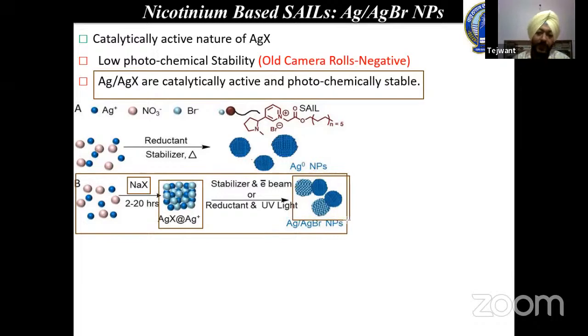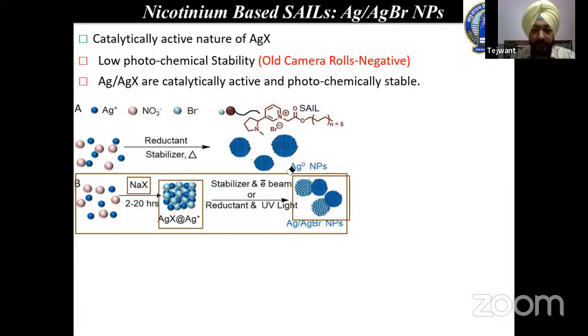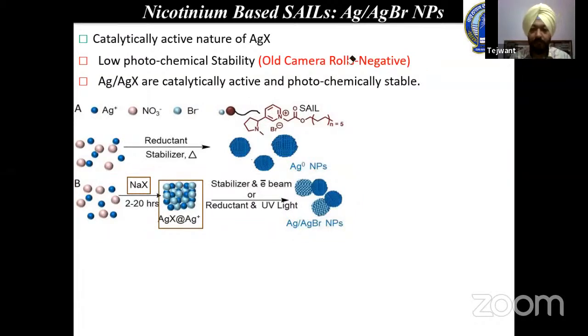Janus means when your nanoparticles have two faces, we can say. When you see from any of the faces, the particle looks similar. So those types of particles are called Janus nanoparticles. So in this case, we have seen that you have to add sodium halide from outside. We have to keep the solution for 2 to 20 hours, so you have lost a lot of time. You have to add certain stabilizers or some reducing agents. Then we need a high energy electron beam or dangerous UV light for the photoreduction of silver at the surface of silver halide to get silver bromide Janus nanoparticles, as I have shown you there. Okay, so we need a certain set of things where one can easily produce these nanoparticles.